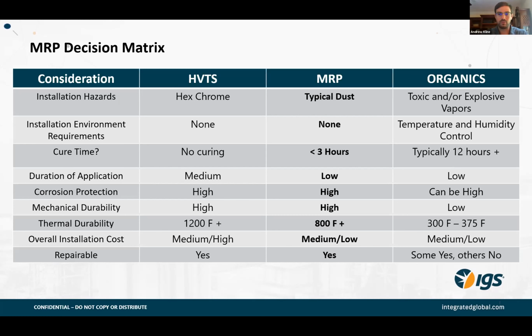As we talked about, the repairability. Some of the organics are repairable in local areas. Some of them aren't. But both the MRP and the HVTS are easily repairable on a small area. And the other thing to mention is another thing that causes failures over time with a lot of the organics, the concept of saturation over time. Think of the coating as a very non-porous sponge, but still has some porosity. And that corrosive media over time impregnates its way into some of the organic options. And once it reaches the layer that it's able to get to that substrate and that coating gets saturated, the system delaminates and comes off the wall.